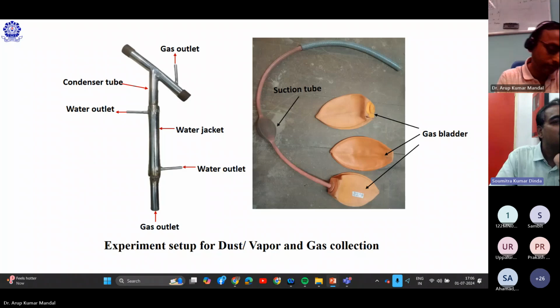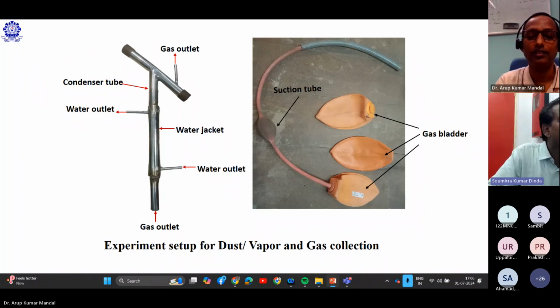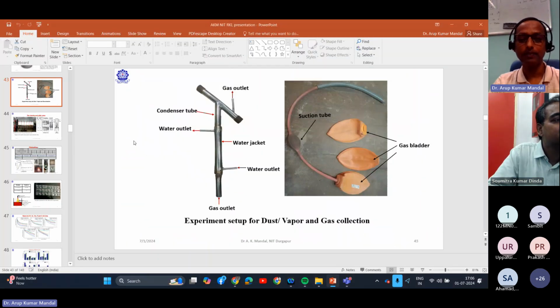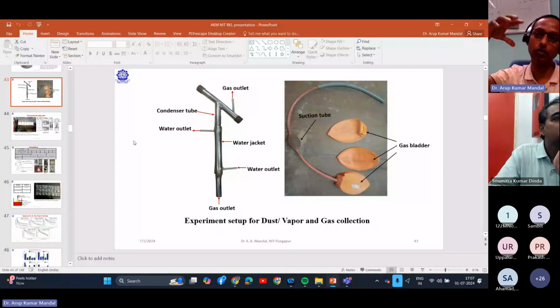And one more question: how deep will the effect of that plasma be in the molten material? It will concentrate only on the surface and remove only the impurities on the surface. Actually, plasma has some impingement velocity. The arc has some impingement velocity, therefore some ions, hydrogen plasma, go inside also. But majorly the hydrogen reacts at the surface of the liquid metal. Due to the impingement velocity of the arc, or the arc pressure, some amount of hydrogen plasma goes into the solution also.